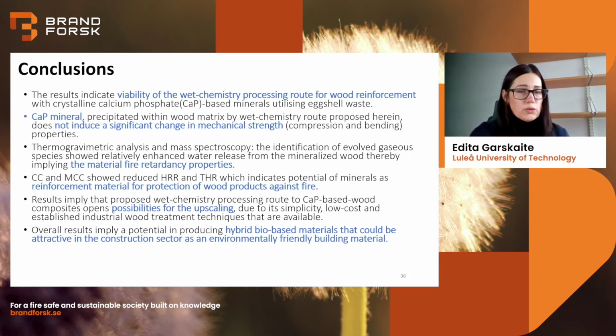So, conclusions to sum up this work, I can say that we demonstrated that this wet chemistry processing route is viable. We can achieve and reinforce wood with calcium phosphate minerals. I think this work shows that it's possible to do upscaling, because we also have an industrial autoclave, which would be a second step to try larger scale materials, not only on a micro scale.